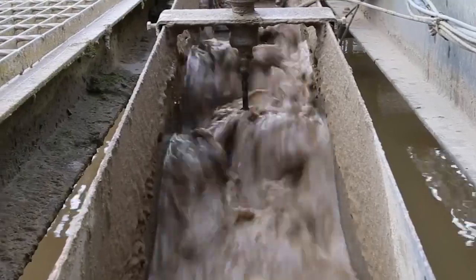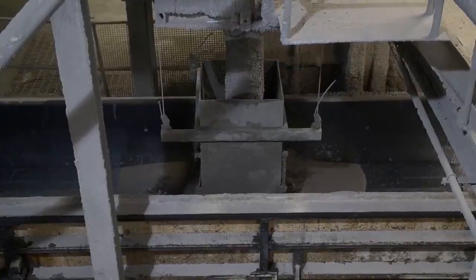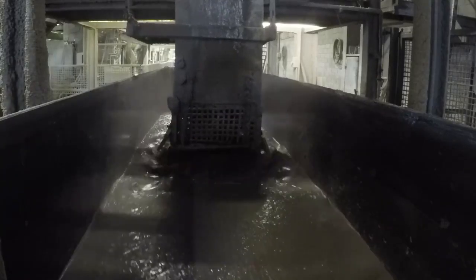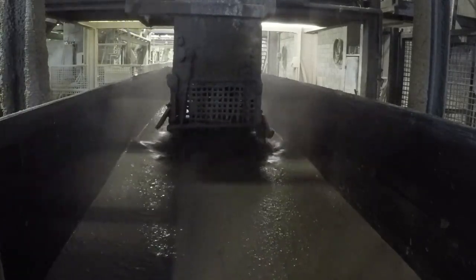Thickened sand is mixed with silt, water, and recycled material from previous batches. The dry ingredients — fly ash, cement, and lime — are then added and mixed for approximately 90 seconds. Powdered aluminium is combined with water to create a raising agent, which is added to the mixture at the end of the mixing process, and mixing continues for around 30 seconds. The precise quantities of each ingredient required depend on which Quinlite block is being manufactured, as each ingredient adds unique properties to the finished block.